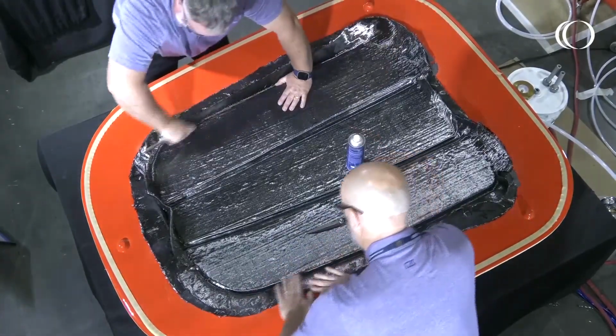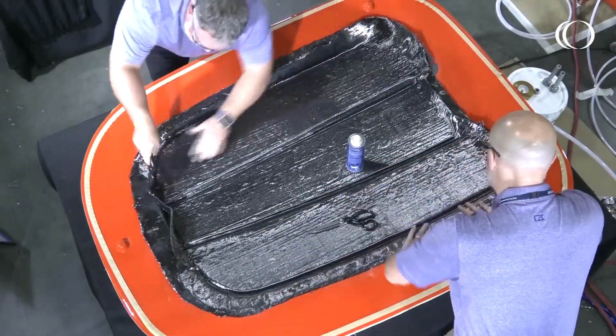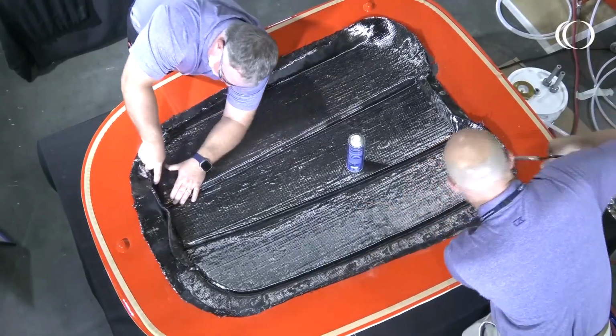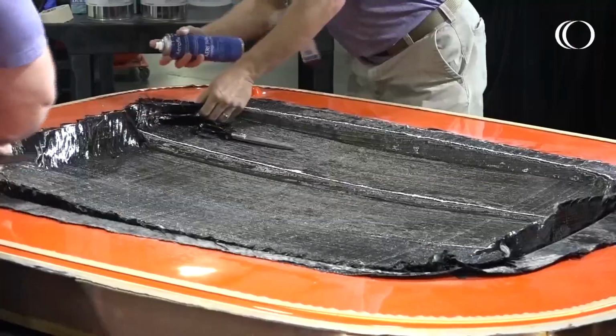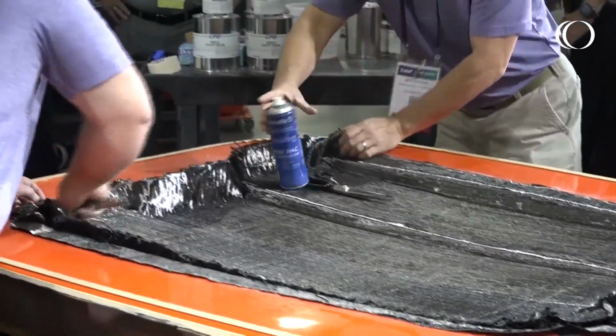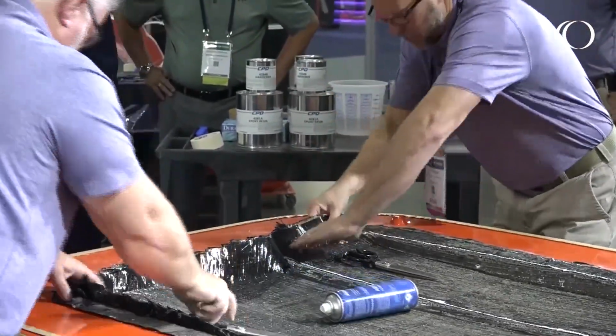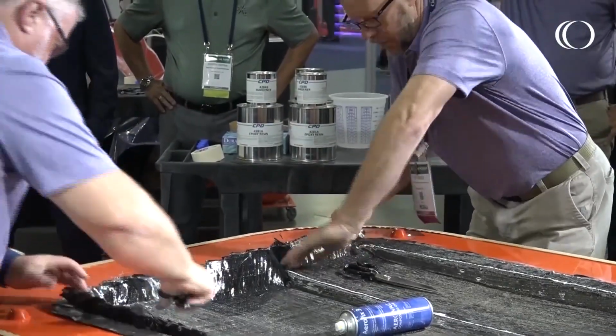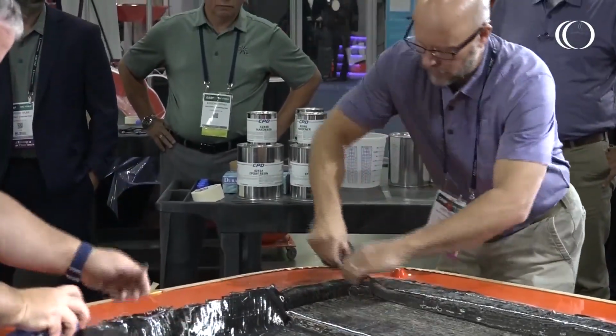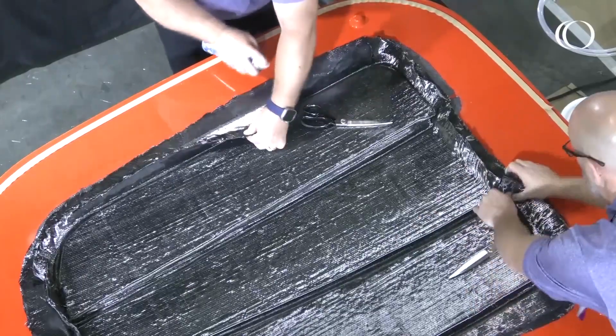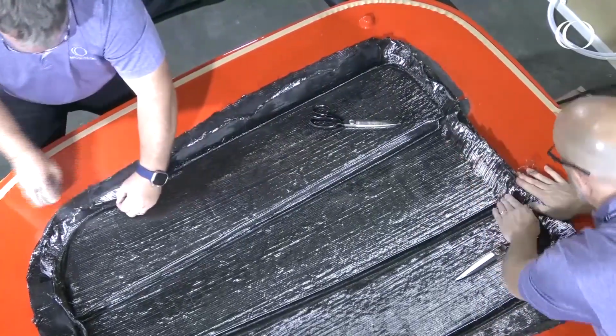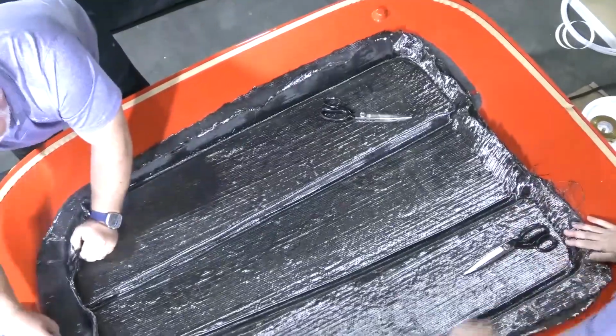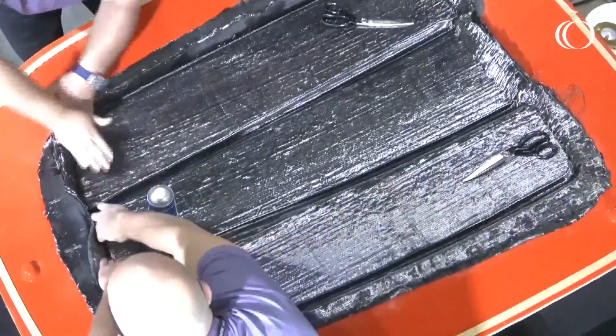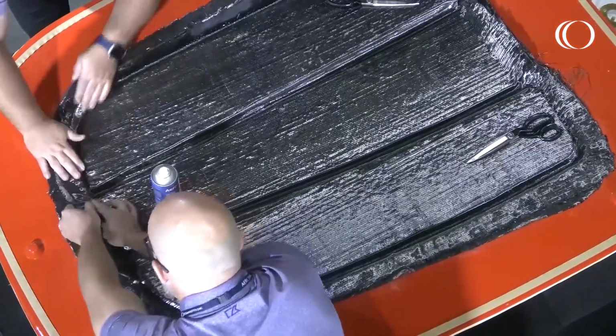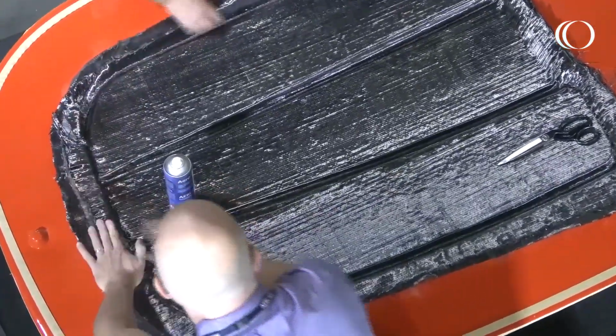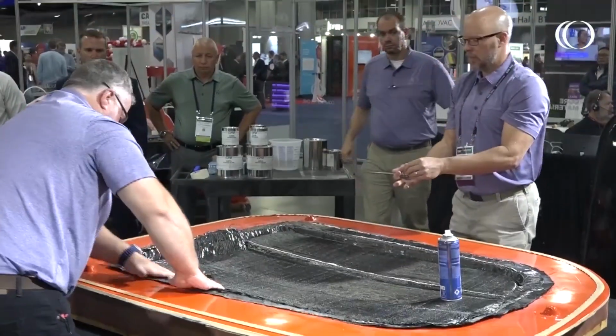But we'll be adding an external flow media to help the resin flow on this part. For pressure, we're only using atmospheric pressure. So full vacuum on the vacuum infusion process, and we have half vacuum on Light RTM. We're using low viscosity resins. In this case, we're going to be using an epoxy resin, and then we'll be using vinyl ester and polyester in the others. And they're low viscosity, like I said, around 100 to 300 centipoise. And as you can see, all the reinforcements go in the mold dry, and then we'll seal everything under a vacuum bag and then inject the resin.